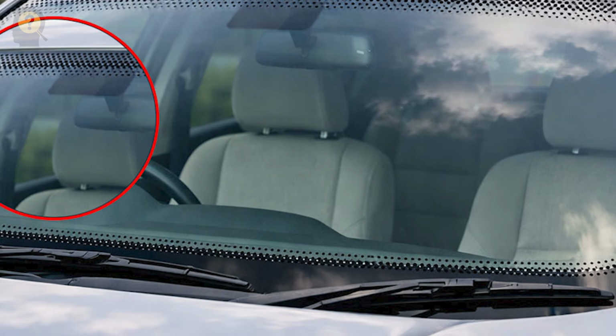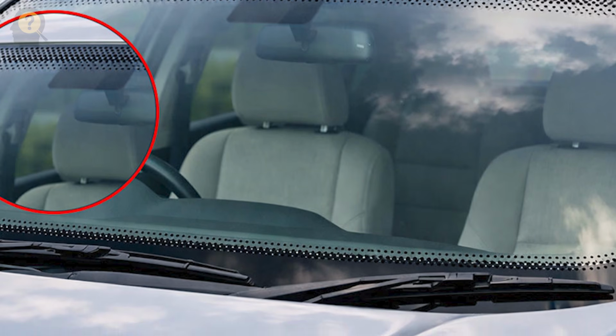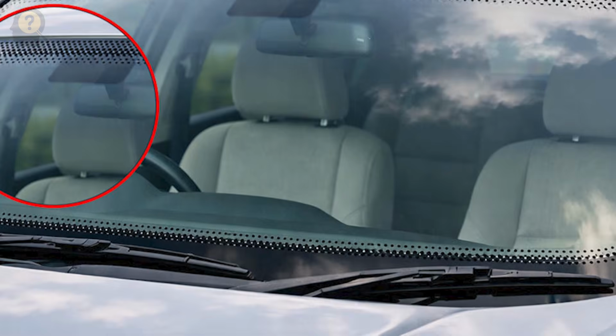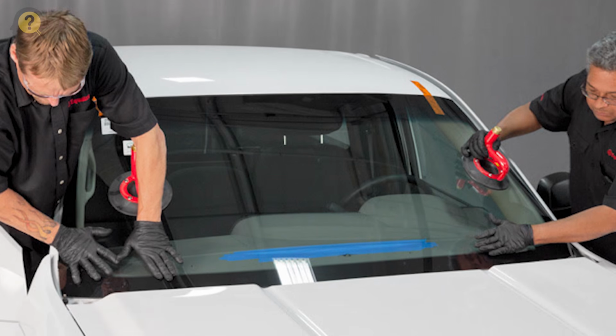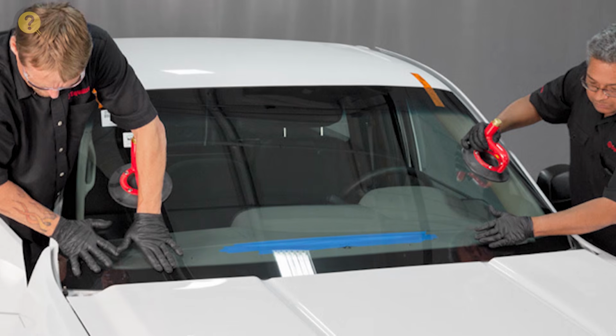But the dot fade does something else too. The human eye is sensitive to hard transitions. A solid black band running across the base of your windshield with a sharp cutoff where clear glass begins would be visually jarring, and in certain light conditions, distracting to the driver. The halftone gradient eases that transition visually, the same way it manages it thermally. And honestly, that's a pretty elegant solution to two completely separate problems using a single printed pattern. One feature, two functions, neither of which most drivers ever think about.